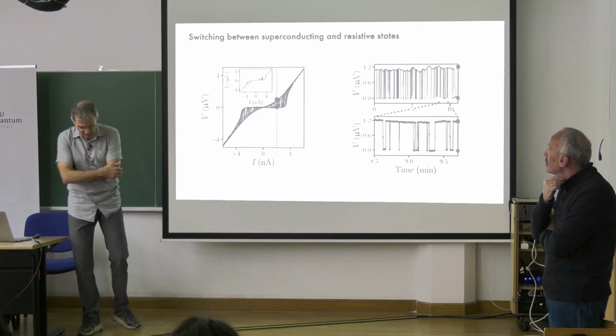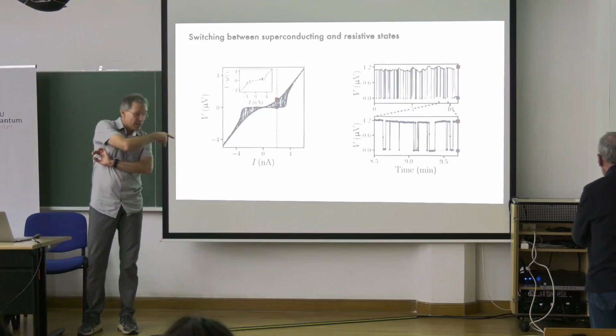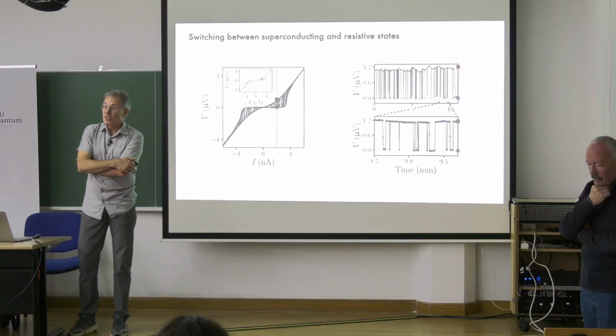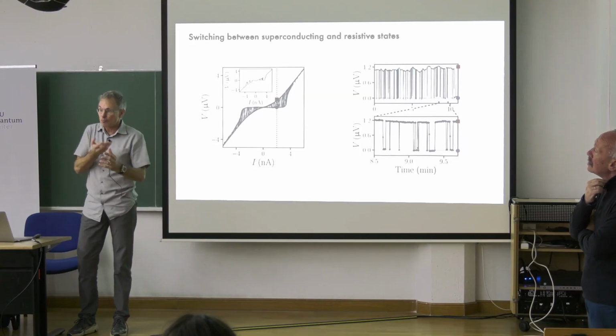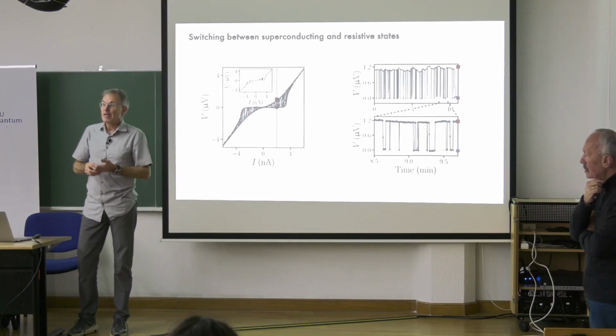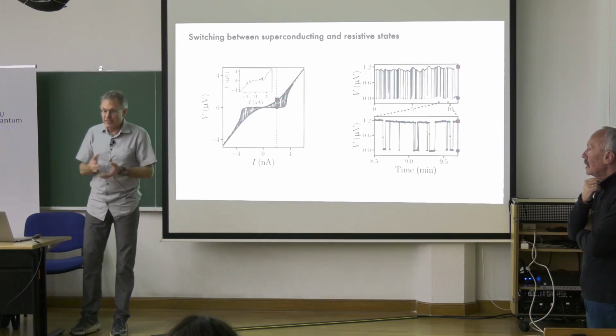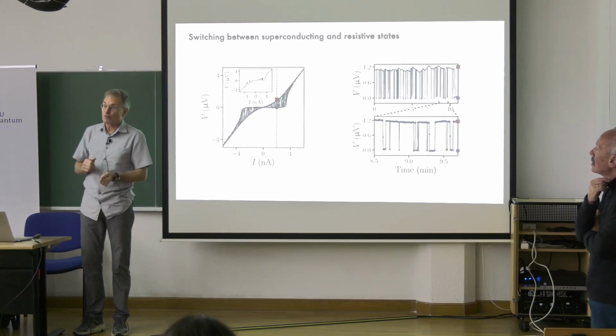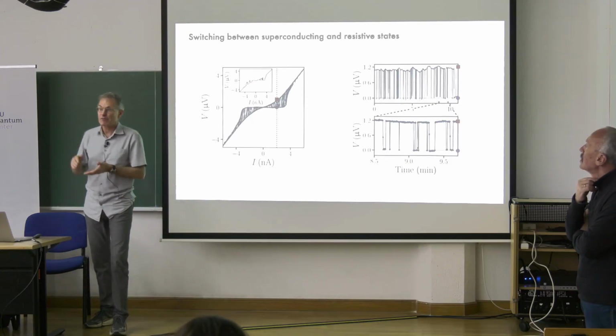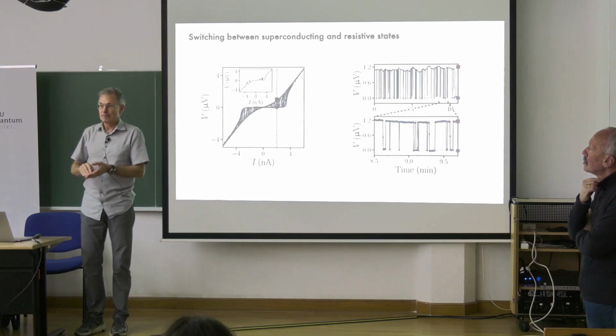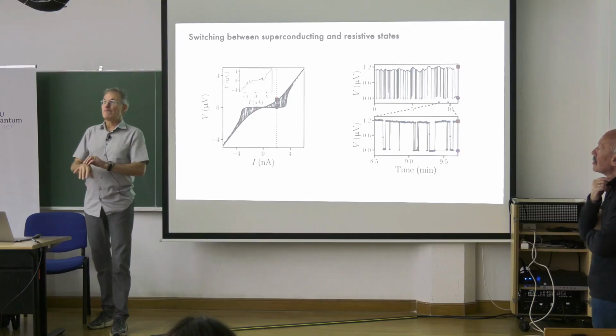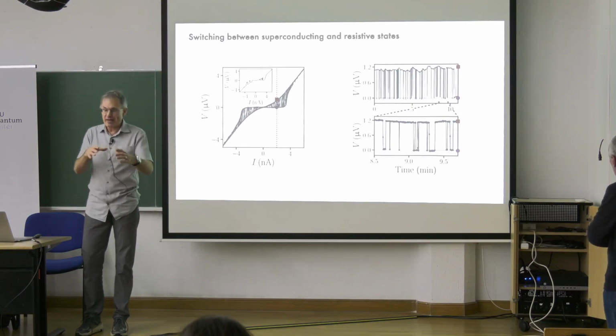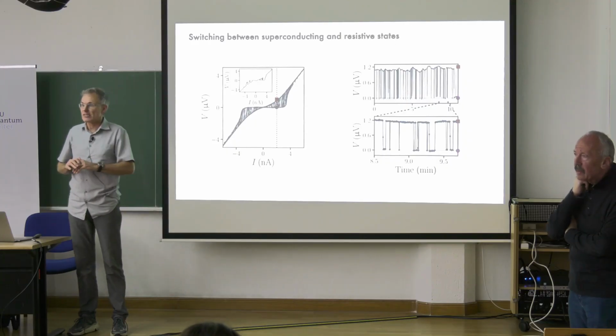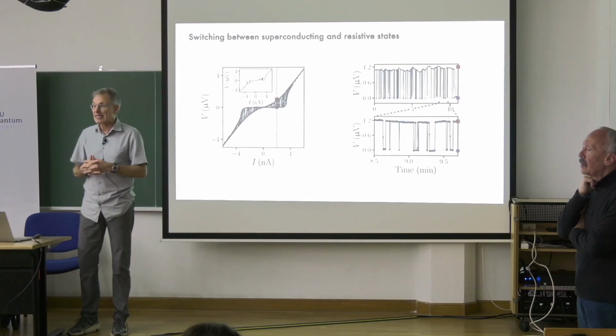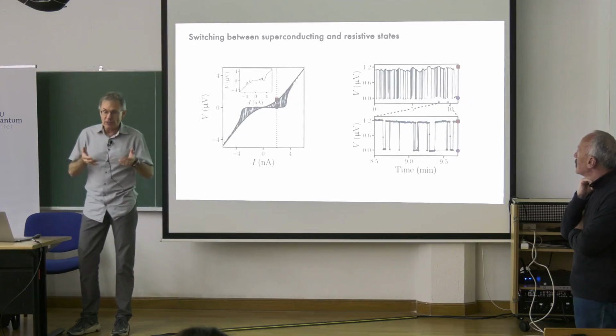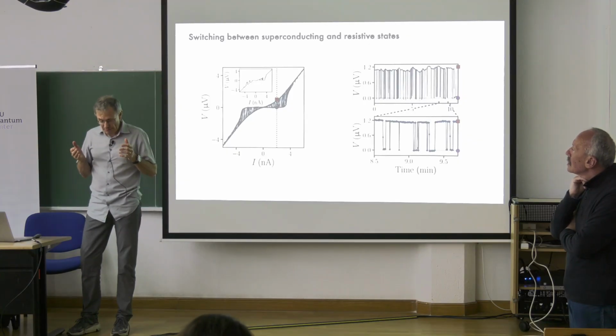I mentioned these two works from Harvard and MIT, where they measure kinetic inductance. Kinetic inductance probes superfluid density directly, and if there is a BKT transition, then there should be a jump of superfluid density, the so-called Nelson-Kosterlitz jump, from some fixed value to 0. Nobody saw that. But if you have finite size effects and so on, then it can be masked.